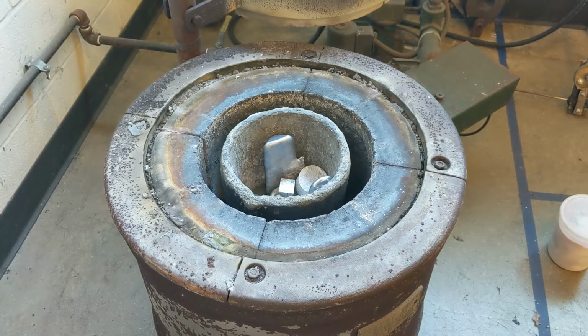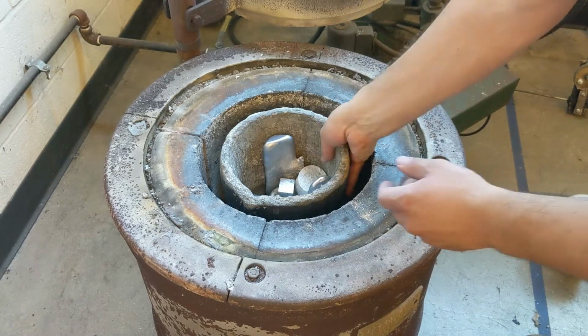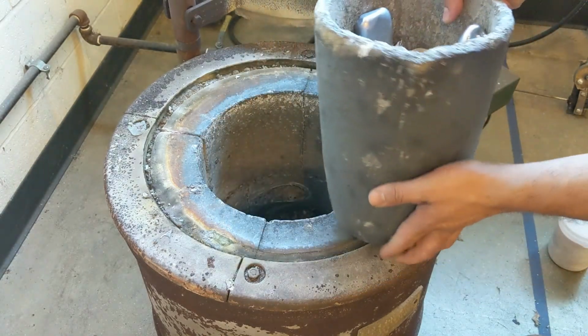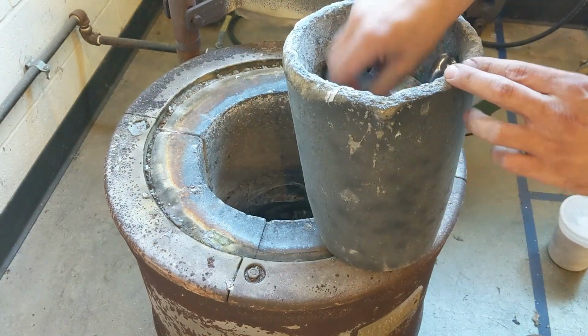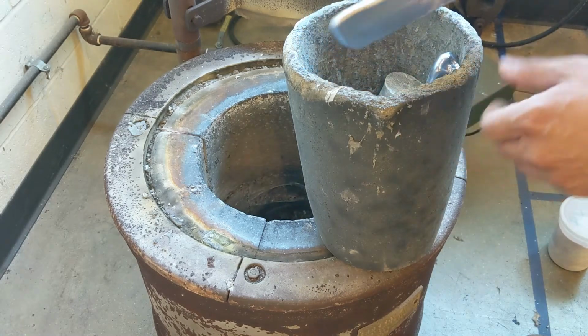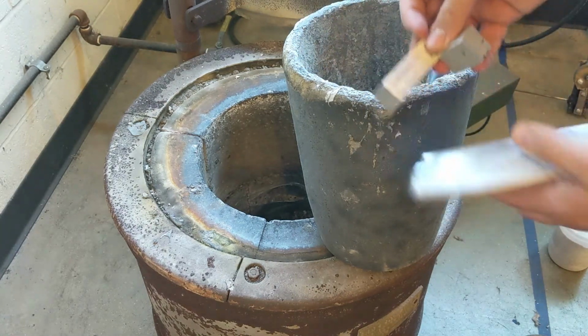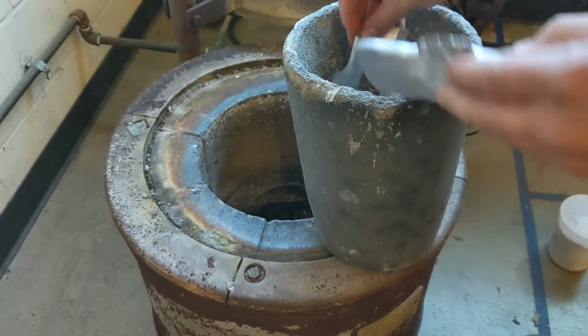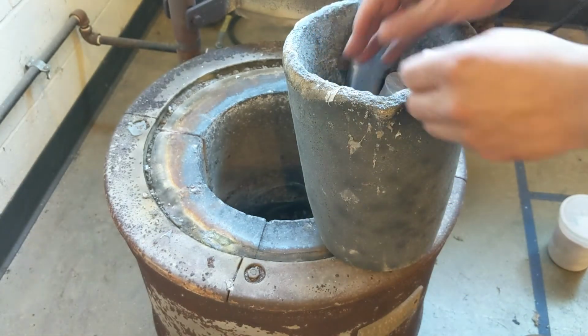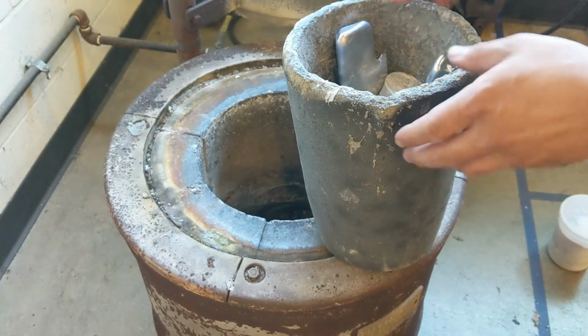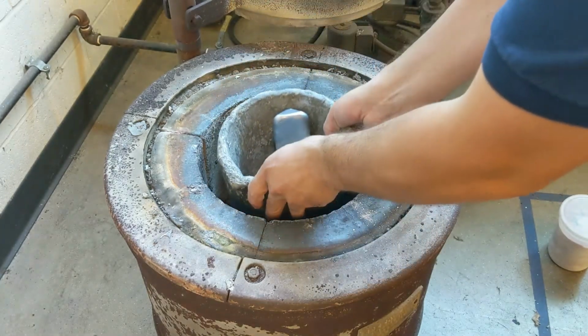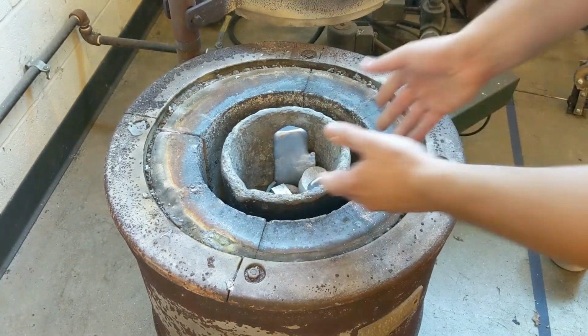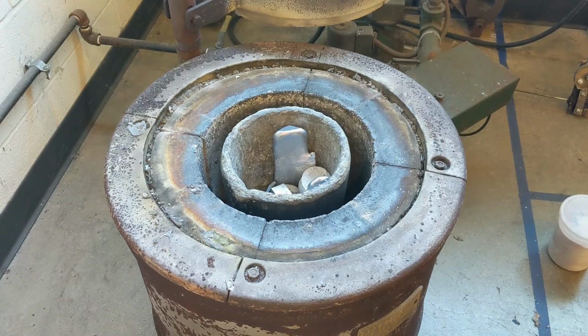We have to take some precautions as well over here at our gas-fired furnace. We have our crucible here, which is a refractory material, and we filled this with some cuttings and trimmings of aluminum, as well as some pre-melted aluminum alloy. And just like in the welding lab, anytime we get this metal to an elevated temperature, we want to protect it from the oxidizing elements of the air.